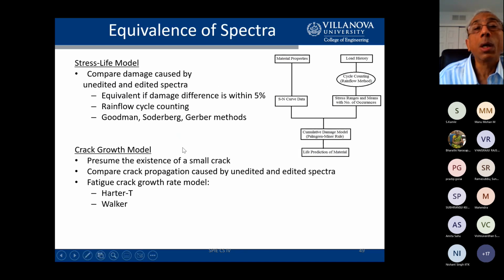And again, as I mentioned, you want to make sure that the full spectrum and the edited spectrum are equivalent, and you do that by making sure the damage is about the same. And we've used both the stress life model and a crack growth model. And all of this, you can do within commercially available software that do fatigue crack growth, for example.